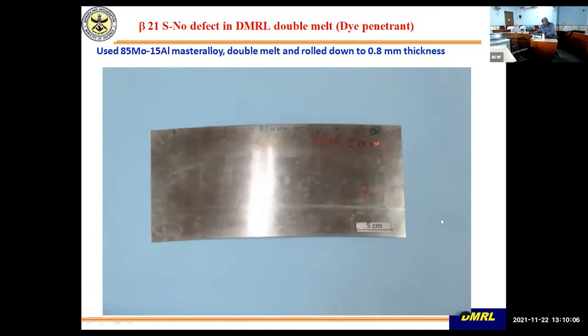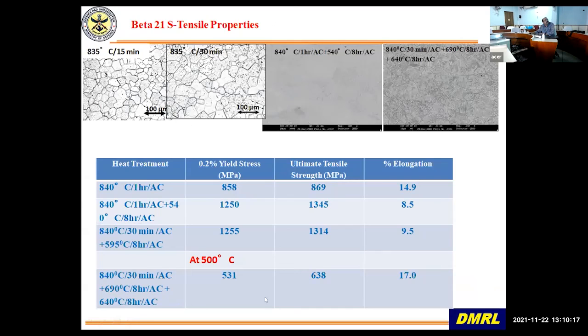So ADA wants it. So we processed this alloy again with 85 moly 15 aluminium, and we could process it to 0.8 mm thickness in the lab. There was no issue, and we did property evaluation in solution treated as well as solution treated and aged condition, both at room temperature and a higher temperature, and we were getting good properties. Here I'm showing you the aged microstructure at different aging temperatures and the beta treated single phase microstructure. You want these sheet materials to be in beta treated form for forming certain components. After you form, you can age the final component to gain strength.